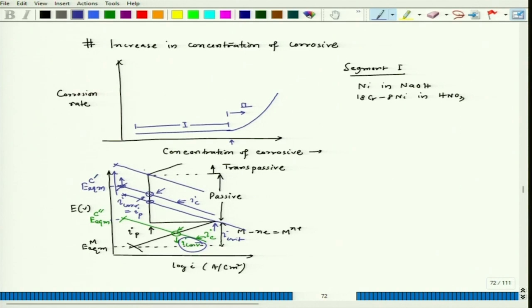But if in that particular environment my passive zone length is very high, let's say this is my passive zone length instead of breaking here. Okay. So if this is a wide passive zone, then I could see that this will be my limiting concentration of the corrosive, where if we increase the concentration a little bit, then it will reach the transpassive zone. So from this concentration to this concentration level, over a wide range, I can maintain spontaneous passivity. That material will go to spontaneous passivity, and then passivity will be maintained.